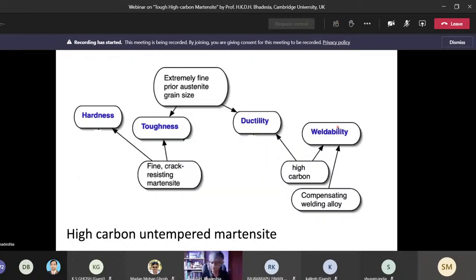And in order to ensure weldability, I cannot have 1.8 weight% carbon. The maximum carbon concentration we have to limit to about 0.4 weight%, so that any martensite which is produced in the coarse austenite grains of the heat affected zone still is not sufficiently brittle. Okay, so our maximum limit is now going to be 0.4 weight% of carbon, and we are not going to temper the material at all. We are going to use the properties of the martensite in the as generated condition after hot rolling.